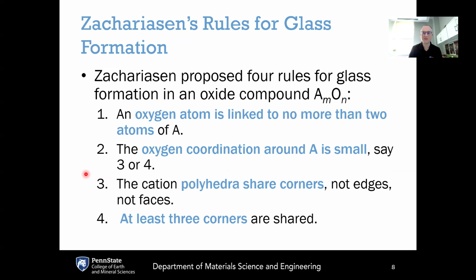These are known as Zachariasen's rules, and these are the most famous rules or guidelines that are used for determining what would be a good glass structure versus not a good glass structure. So Zachariasen proposed 4 rules of glass formation, and he was specifically thinking in terms of oxide glasses. So he considered an oxide compound where there's a cation A, and then the anion is the oxygen. So in the realm of oxide glasses, this would have a general formula of A sub M, O sub N. And the M and the N here just govern the stoichiometry between the cation and the oxygen. This could be SiO2, this could be Al2O3, it could be B2O3, whatever the oxide is.